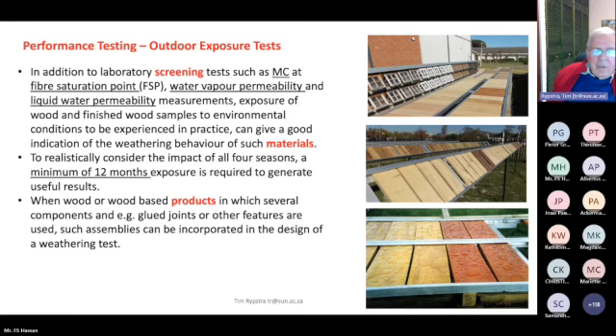So, but to realistically consider the impact of all 4 seasons, a minimum of 12 months exposure is required to generate some useful results. And what you see on the right-hand side there, typically this is not as a result of rain, this is as a result of dew. So atmospheric conditions which are generating dew are quite important, because they are not represented in rainfall figures if one wants to correlate rainfall with the durability or the weatherability of coatings. So when wood or wood-based products in which other components like glue joints and other features are used, then they will also affect the design of the weathering test.